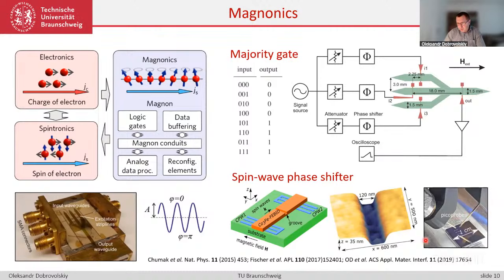And on the right-hand side, you see an example. It's a room temperature experiment, where you have a permalloy film with two needles, or so-called pico probes. So basically a high-frequency signal is applied through these needles, attached to the respective place where the antennas are located, and the rest we cannot see because the resolution here is not enough. The system is nanoscale. Yeah, basically this can be transferred also to low temperatures, and we now need to look at the details of